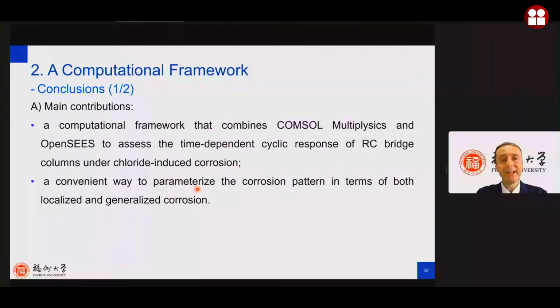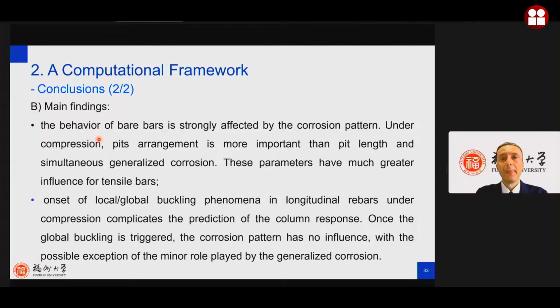And we also try to parameterize the corrosion patterns in terms of both localized and generalized corrosion. And this was done mostly based on engineering considerations. And this is, from my point of view, really important. So we need to do research, to go in depth, but never to lose our engineering knowledge. And the behavior of bars is strongly affected by the corrosion pattern. Under compression, the pit arrangement, so the localized corrosion, is more important than the pit length and the generalized corrosion. It means where the localized corrosion is, is more important than its length.